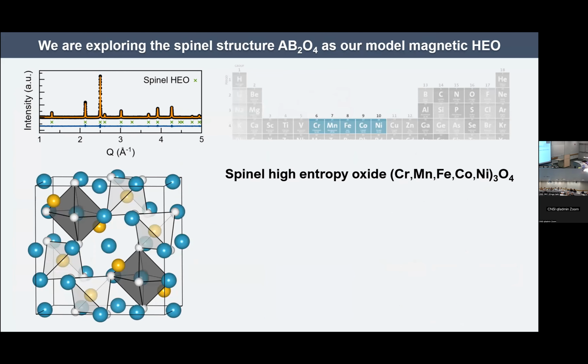Okay, so my representative high entropy material that I'm going to be speaking about today is a spinel high entropy oxide. And it's made up of the 5 elements that go across the transition metal block in the 3D row. So everything from chromium up to nickel. And again, they're in equal proportion, so an equal ratio of those 5 elements. And if we mix them together under appropriate conditions, we can indeed form a single phase material, as we can see from this X-ray diffraction pattern.